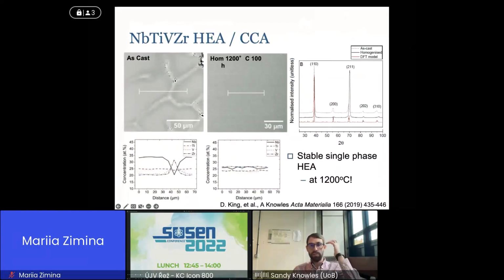So we then went and produced these alloys experimentally. One of the cautions in many high entropy alloys is how they're produced. They're often formed with very high cooling rates, and one of the questions is, are they truly stable? For us, as we want to use these materials in a nuclear reactor, they're going to sit at a high temperature for a long time. So they do need to be temperature stable.